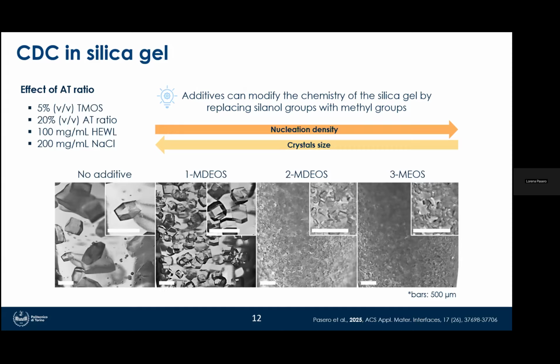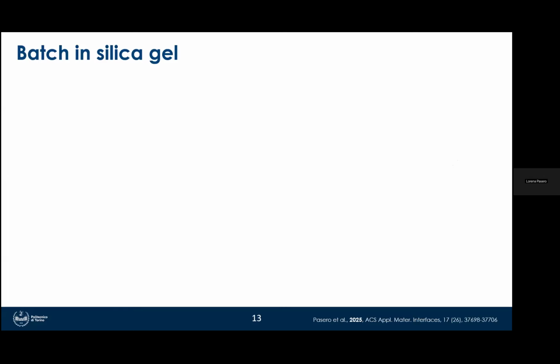And we could also see that the effect of methylation reached a sort of plateau. So after the inclusion of 3 methyl groups, there was a saturation effect, since no significant difference in size and number of crystals was appreciated between 2 and 3 methyl groups. So to better investigate this first screening effect of these additives, we moved to the batch crystallization.